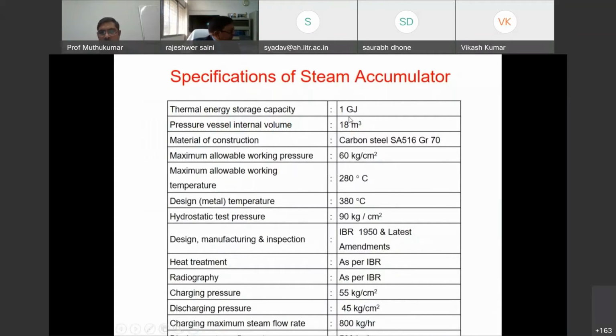And this is the specification of the steam accumulator. The designed capacity was 1 gigajoule. The vessel volume is about 18 meter cube. Then design pressure is about 60 bar, but tested up to about 90 bar, hydrostatic test pressure, and everything is designed as per the Indian Boiler Regulation. The charging pressure is 55 bar, and discharging pressure is 45 bar, and here heat is stored at about 220 degrees Celsius.